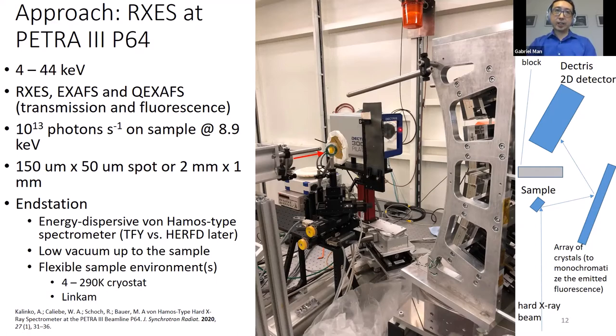So as a hard X-ray beamline, it's really nice because the sample environments are quite flexible. So in my case, I used a Linkam flow stage to flow nitrogen around the halide perovskite crystals to try to mitigate air exposure.